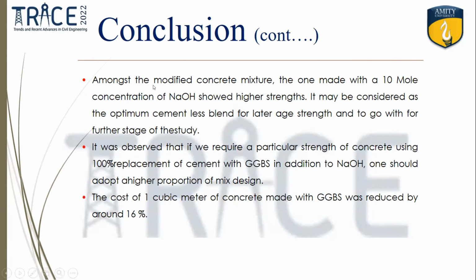Next conclusion was, amongst the modified concrete, that is the GGBS concrete, the 10 mole concentration results were best. If I'm suggesting to replace the cement by 100%, we have to adopt a higher proportion of mix design to achieve the target strengths. And also, the cost of construction for every cubic meter of concrete, compared to conventional concrete, GGBS reduced the cost by 16 to 20%, depending on what GGBS class and what NaOH concentrations you're using.